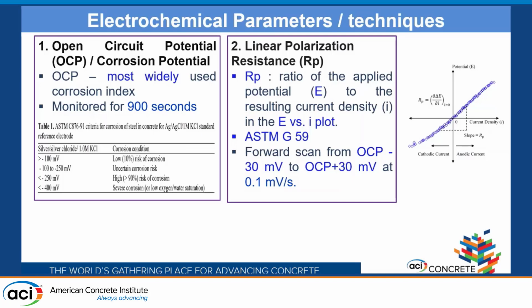The second technique which we are using here is linear polarization resistance. In short, this is called Rp. Rp is the slope of the E versus I plot, which is obtained from a forward scan from open circuit potential minus 30 millivolts to plus 30 millivolts at a scan rate of 0.1 millivolts per second. So this is a sample Rp plot.